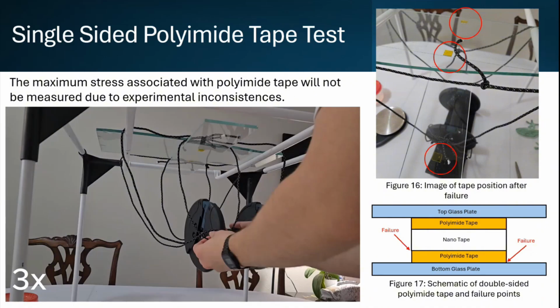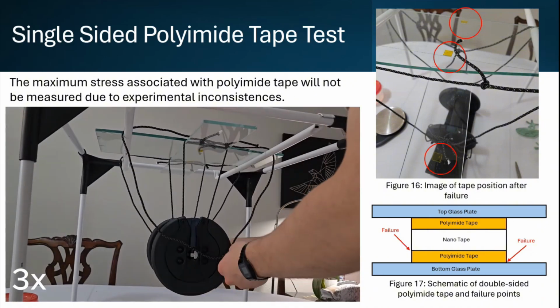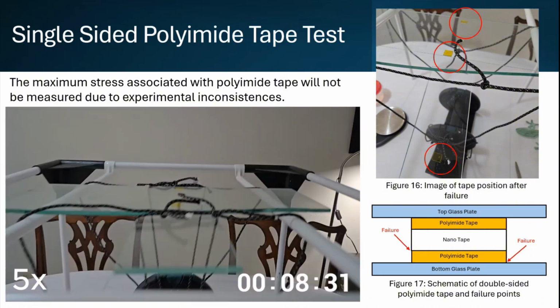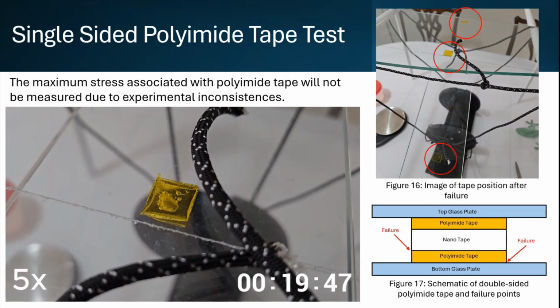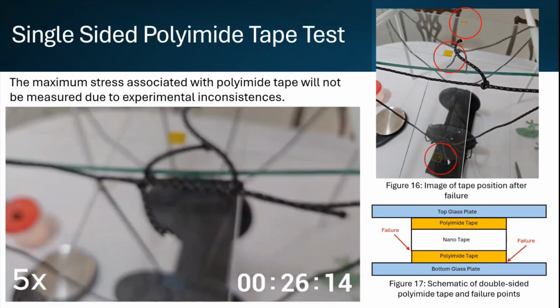So when I was testing the maximum stress associated with the polyimide tape, it wasn't consistent in which interface that it failed. So the polyimide tape is single-sided, and to make it double-sided, I did like a loop, and it couldn't even hold the glass. So I figured I'd put nanotape in between 2 pieces of polyimide tape, the polyimide tape contacting the top glass plate and the bottom glass plate, as seen in figure 17.